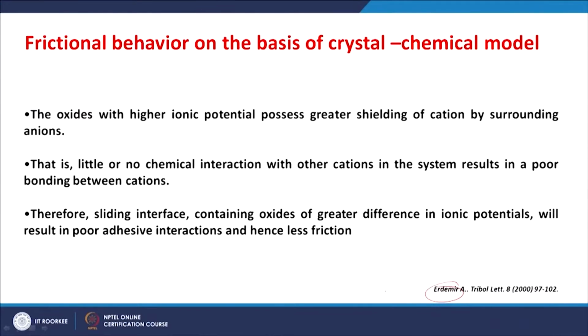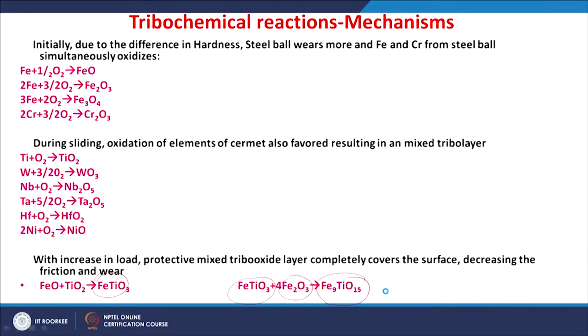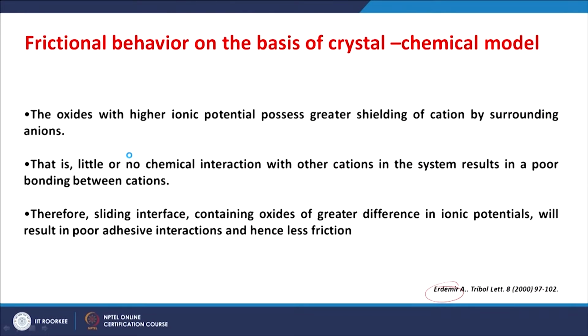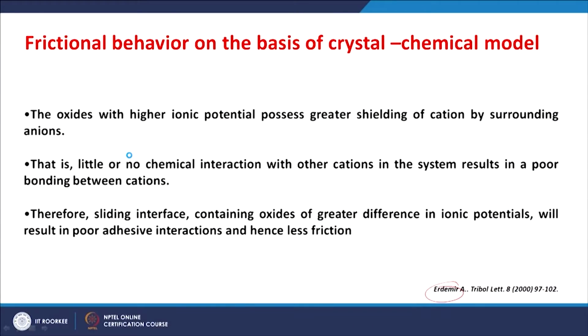The friction behavior can also be understood by a crystal chemical model proposed by Gardos. So, as we have seen, there is a chance that several oxides are formed on the surface at the contact. So, the oxides with higher ionic potentials possess greater shielding of that cation by surrounding the anions. So, the cation has little or no chemical interaction with other cations in the system. So, the sliding interface which is rich with the oxides of a very large difference in ionic potentials will result in very poor adhesive interactions. So, it actually contributes to the lesser friction.